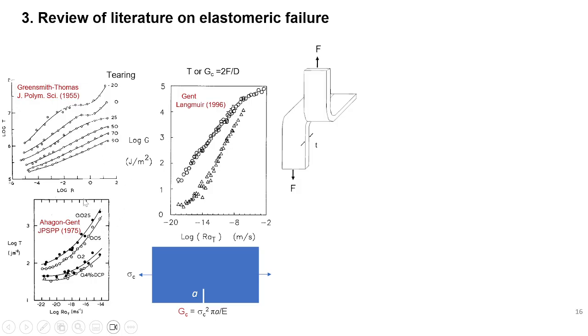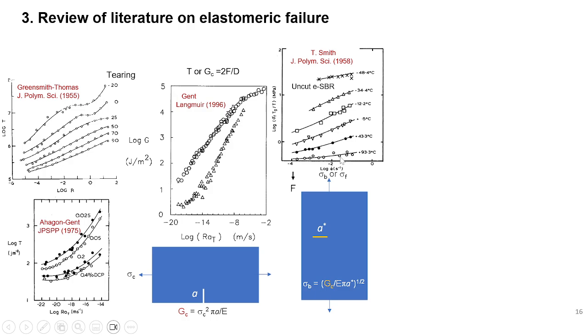And then you find at lower temperature, it's more resistant. That's well known for 70 years. What people tend to ignore is a parallel universe where you don't make any intentional cut. You just prepare a nice dog bone or a ring, as we often do. And then, without any cut, you try to stretch until it breaks. So you get the tensile strength. And similarly, you find the tensile strength grows with rate and grows as you go to lower temperature.